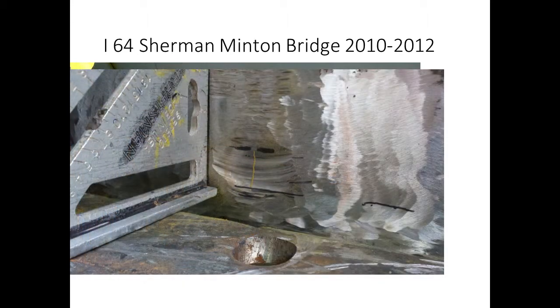And we can go back to September 9th, 2011. I know where I was, and I know where David Steele was, because we were on the bridge. After they cut one of these loose, they found a small surface breaking crack. They had a non-destructive testing technician come in, and he did ultrasonic shear wave testing and said that he found that the subsurface of the crack was about 2 inches long. That information got passed up the chain of command, and at some point the Indiana DOT decided to close the bridge to traffic